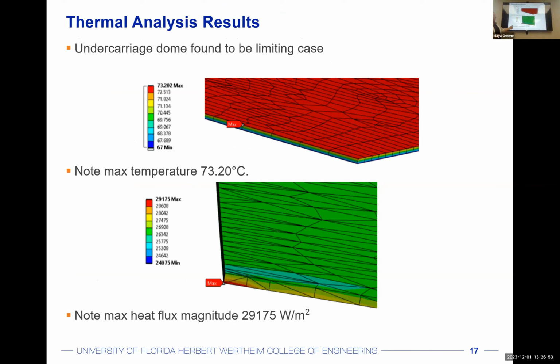Furthermore, we see the heat flux magnitude is at its maximum in this corner. That is expected due to the highest delta T that will be experienced. And that maximum magnitude was around 29,000 watts per meter squared.